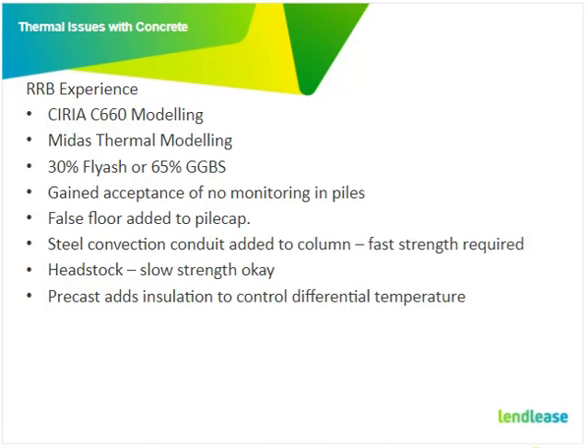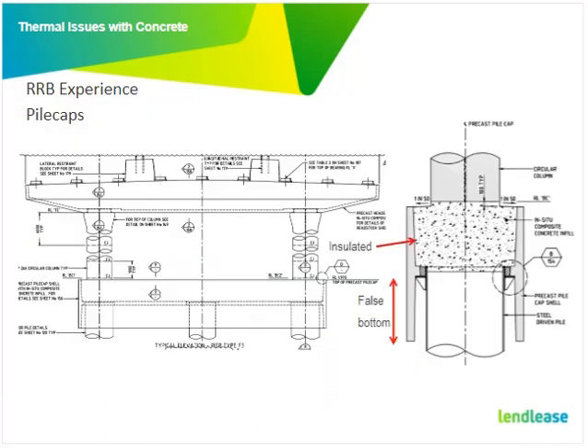So some of the other things, I'll probably talk about what we used on Richmond River Bridge that helped us as well. These are our pile caps. What we have here is a precast shell that you just applied directly over the top of the pile. Now typically your pile cap needs to go to the depth where we've got the soffit there, but what we did was create that as a false floor, so we reduced the thickness of it. So that definitely helped us significantly to control the peak temperatures. And the other benefit you get is you've got a shell that automatically insulates that face of the concrete, so you don't have any differential temperature issues resulting in that. So, false bottom, insulated.